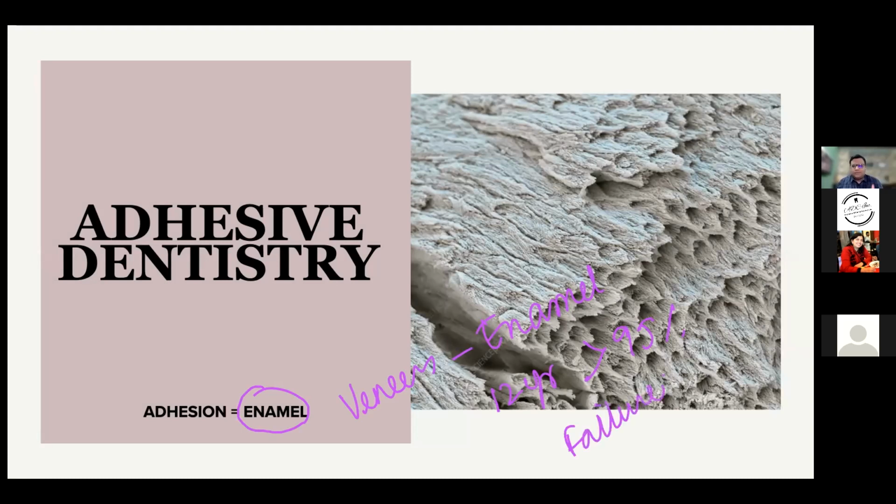So what does this prove? That enamel is the only bonding that you can actually trust till date, and that stays put over a period of time. I can show you bonding to dentine which goes up to 40 to 50 megapascals. Using the right bonding methods, you have very high bond strength. But the problem is, once the bond comes into function, once matrix metalloproteinases get released, the resin dentine bonds will disintegrate over a period of time.